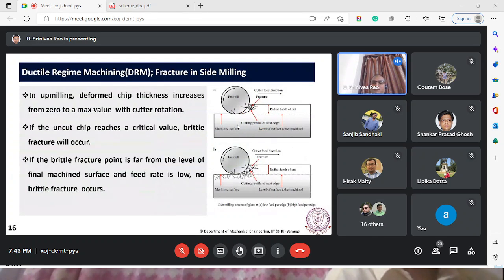This is further explained in case of up milling. Here it is 0 to maximum. In this zone, no cracks are formed. And in this zone, the cracks are formed. And if the radial depth of cut is further increased, then the machined surface will also have cracks. So we need to take care of some critical value of uncut chip thickness. We have to keep it below that, otherwise brittle fracture will happen.